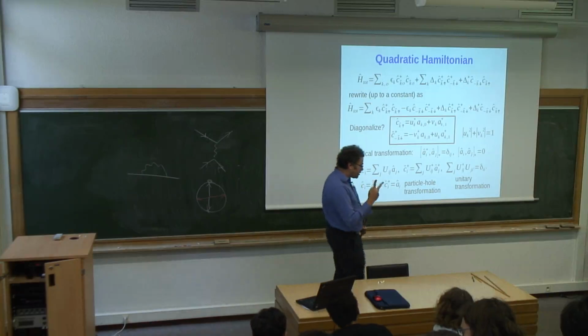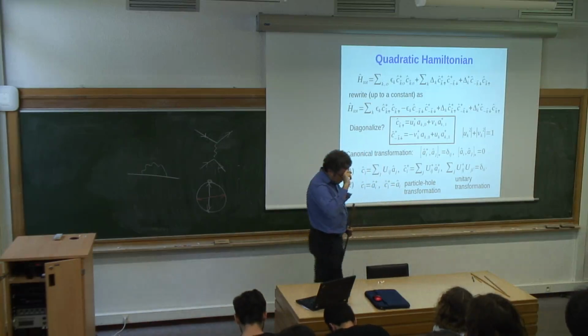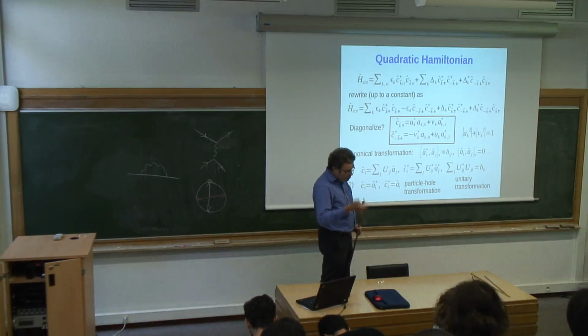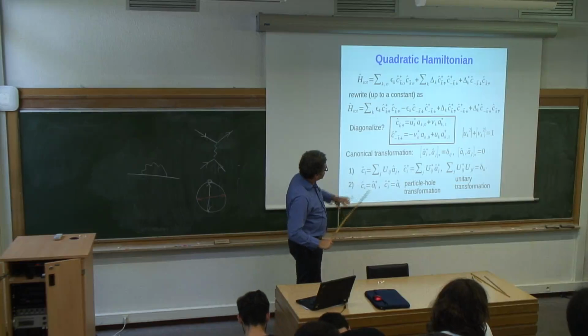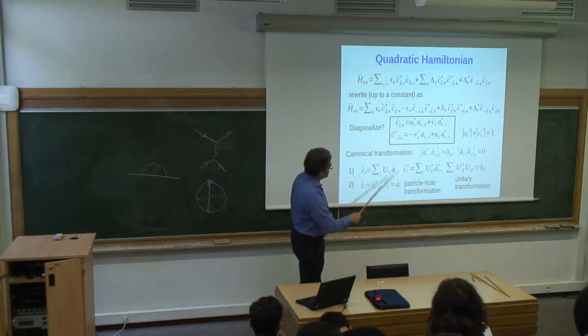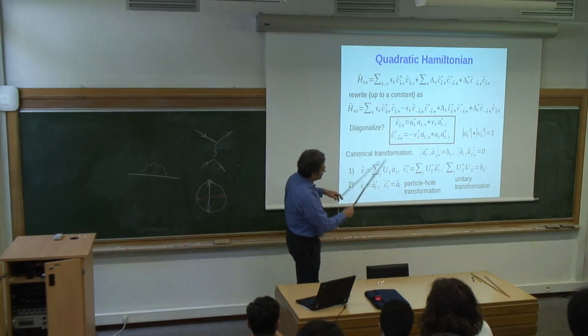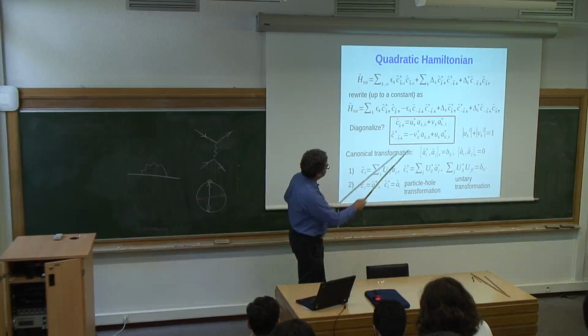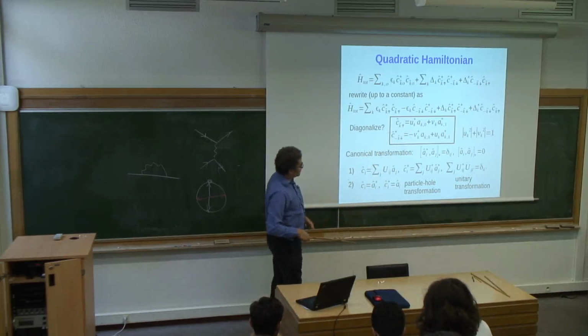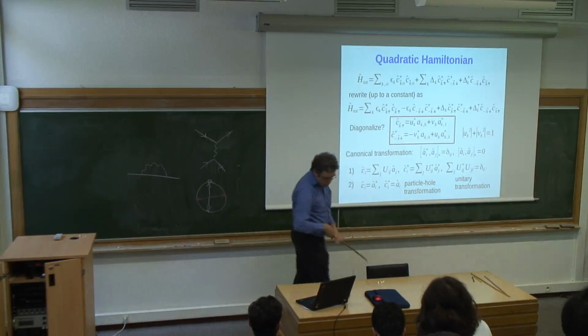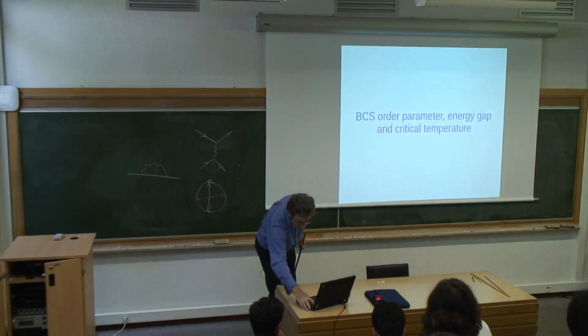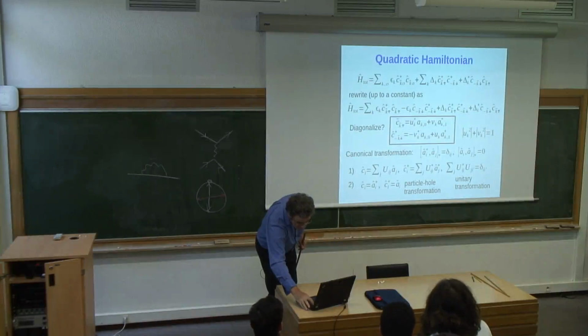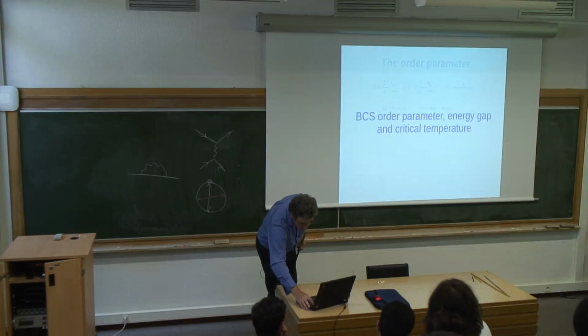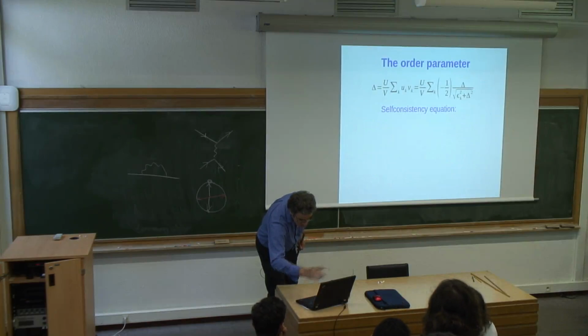If you take creation and annihilation operators for fermions, you can interchange them, and that amounts to replacing particle state by hole state and vice versa. And that's a canonical transformation. So these canonical transformations are kind of a mixture of both of these. We're doing this and that at the same time, and using this canonical transformation, you can check it's canonical, it preserves commutation relations. You can diagonalize the Hamiltonian and obtain the quasi-particle spectrum.